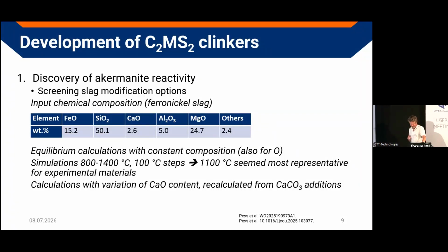But what we did in the beginning of the development of the calcium-magnesium silicate clinkers is we were working on magnesium silicate materials, like this slag, for instance. This is mostly a very silica-rich slag with a lot of magnesium and also a little bit of iron in there, which we couldn't carbonate, so we tried to modify the slag to make it more carbonatable.